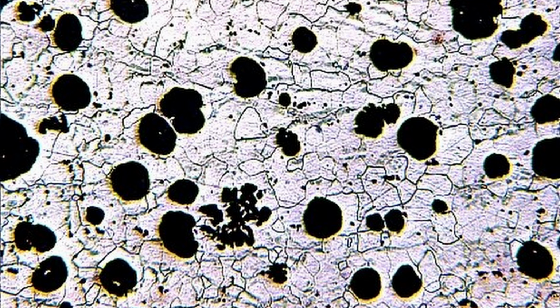Within this molten soup, a number of reactions are happening simultaneously. The oxygen atoms that came with the iron debond from the iron atoms and rebond to the carbon from the coal coke. This releases a lot of carbon dioxide and carbon monoxide. Slag forms by further contaminants bonding to the limestone. All of this results in a significant portion of the iron being liberated from these impurities. But there's a catch. The introduction of the carbon from the coal coke means that the iron that is liberated incorporates a significant portion of the new carbon. And when the tap is opened, the resulting iron mixture is approximately 4% carbon.